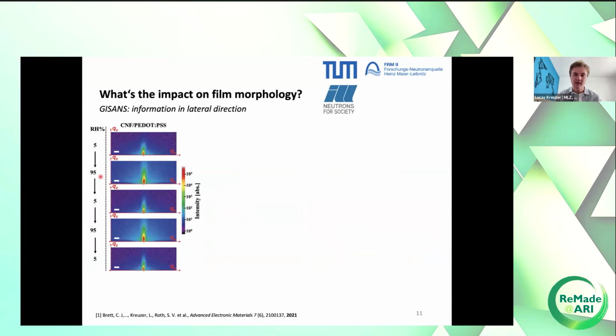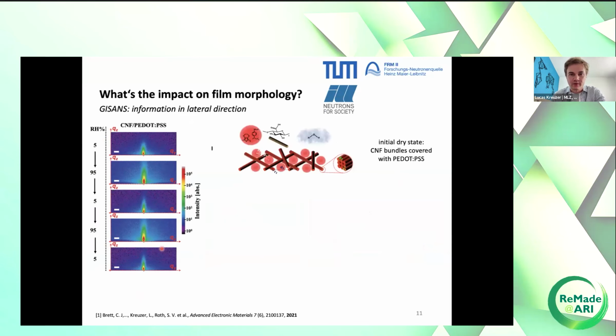So once again, we have 3 cycles of low and high humidity. And these are the 2D scattering images already in Q space. So we have QZ and QY. And from this, with the analysis I just showed on the last slide, we can then extract a morphological model, which I briefly want to show you here. So basically, we have 3 different components. We have these red spheres indicating PEDOT:PSS rich domains. We have these brownish bars. These are the cellulose fibrils. And then we have these cloudy things.